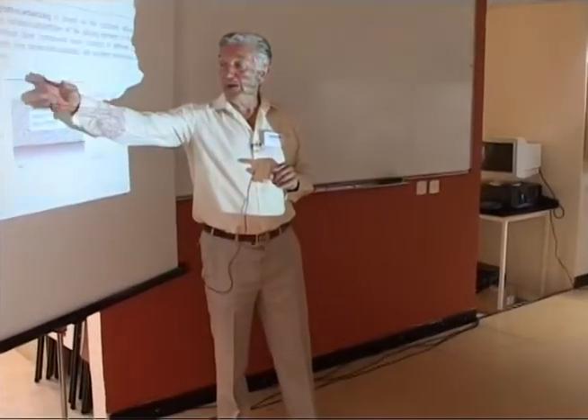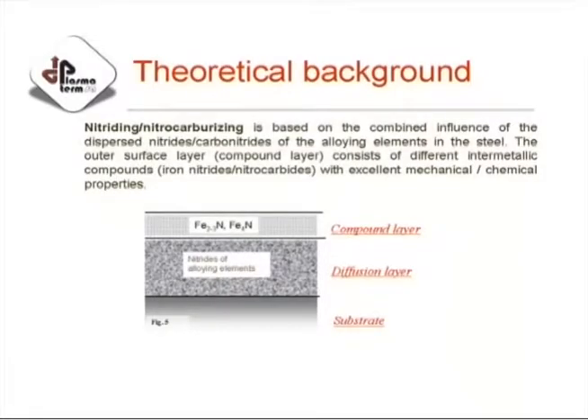Well, when we shift to nitriding or nitrocarburizing, because in this respect there are not two big differences between the two, you will have a compound layer on the surface which consists of nitrides or nitrocarbides. Then you will have a diffusion layer which contains nitrides of the alloying elements, and it gives a support. This is a support layer, and then the substrate.